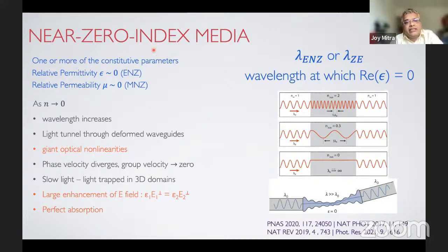What we define in near zero index media are systems where one or more of its constitutive parameters, like the epsilon, the relative permittivity, or the permeability, is very close to zero or is zero. Typically I'm going to speak on systems which have the relative permittivity, or epsilon, of the order of zero, and that's ENZ, epsilon near zero media. They are characterized by the wavelength at which the real part of epsilon actually goes to zero. Now, if the real part of epsilon goes to zero in a lossless media, it is rather easy to understand that the refractive index of the material will also approach zero, because n goes as root epsilon, and therefore that would also go to zero.